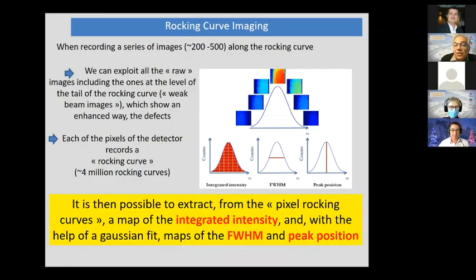When recording a series of images, say 200 to 500, along the rocking curve, which is the diffraction curve, we can exploit all the raw images, including the ones at the tail of the rocking curve. These are the weak beam images, which show the defects in an enhanced way, and each of the pixels of the detector records a rocking curve. So we have 4 million rocking curves recorded simultaneously. It is then possible to extract from the pixel rocking curves a map of the integrated intensity, and with the help of a Gaussian fit, maps of the full width at half maximum and peak position.